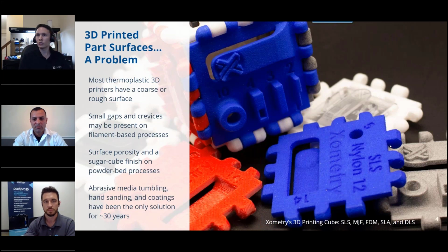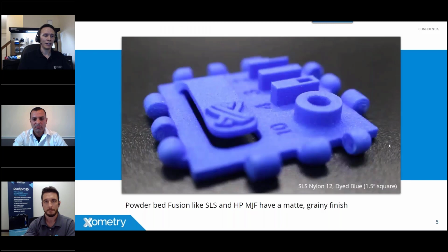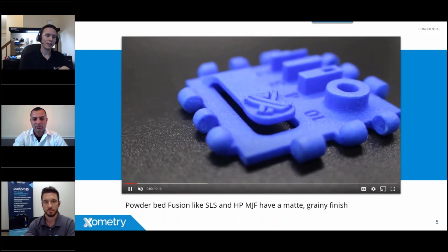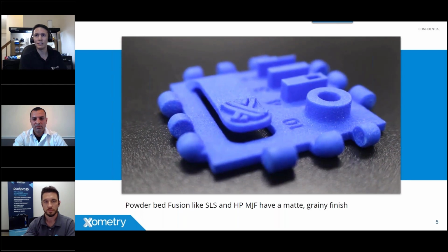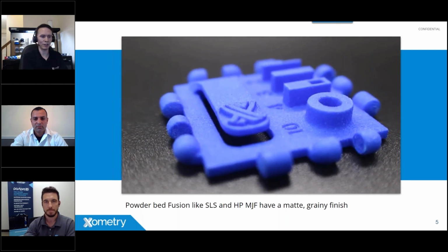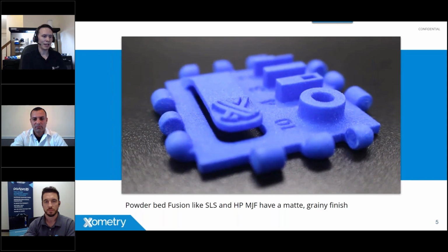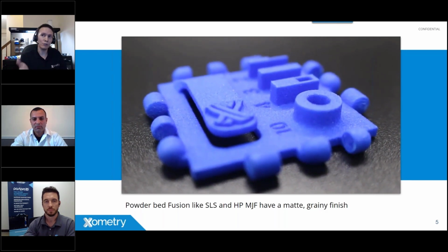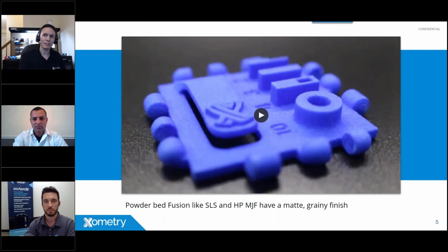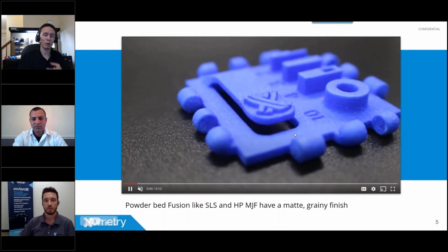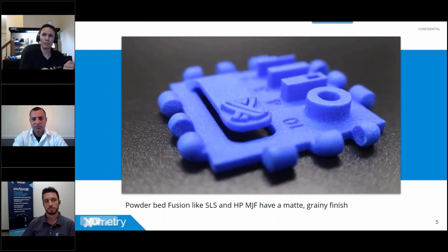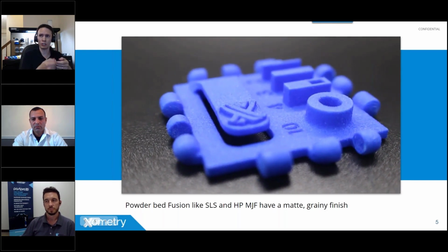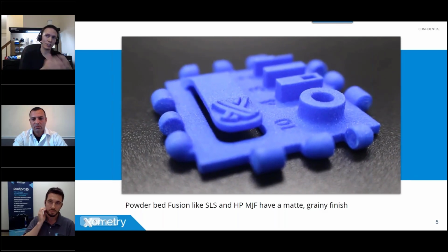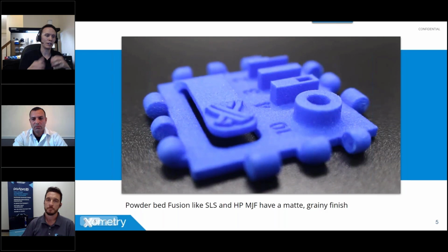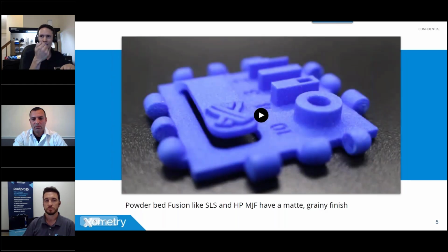And to show you a close-up of what additive parts typically look like, they're not ugly, but again, the surface can still be a consideration here. So this is about a 1.5 inch tile of selective laser sintered parts. This is actually part of our sample cube that we have at Xometry. This is made in selective laser sintering, which fuses powder material together. Both SLS and another process called HP Multi Jet Fusion have similar results, where the outer surface in its natural state feels almost like a sugar cube on the outside. So although the material is solid on the inside, that outer surface can still have some issues, including that if you have greasy hands, they'll take your fingerprint right on the edges too.